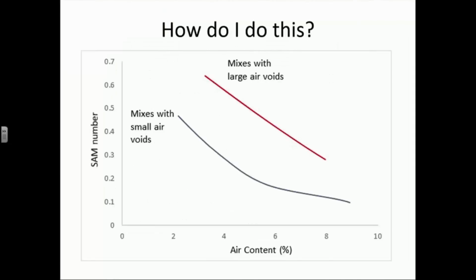So how would I do this? This is a brand new tool. Brand new tool. Okay, this is very cool. This is a plot that you can make out of the two parameters that come out of the super air meter. The x-axis is your air content, or your air volume, and the y-axis is your SAM number. Remember, these are the two things that come out of the super air meter. And mixtures that have large air voids plot near the top red line. And mixtures with smaller air voids plot near the bottom line. And don't think that you're going to be on one line or the other. There's like a whole continuum here.